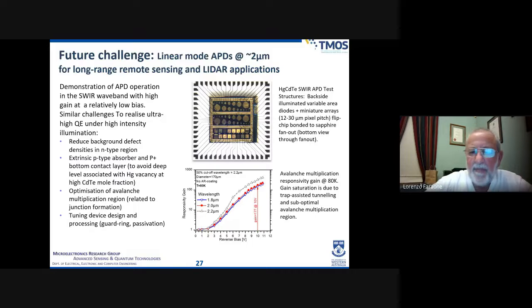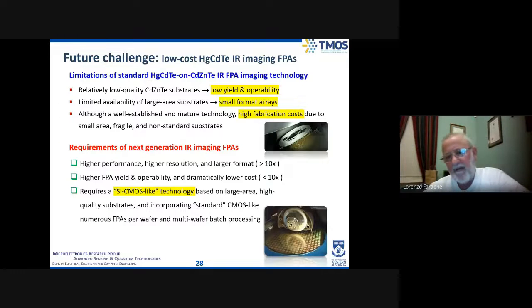This shows some preliminary results from some of our devices, which are not quite linear yet, but we'll get there. You can see here you can get a gain - this is a 2.2 micron cutoff, so around 2 micron wavelength. You can see that you can get a gain of around 100 when you apply about 8 volts in reverse bias. So those are the two challenges we've set ourselves in terms of devices.